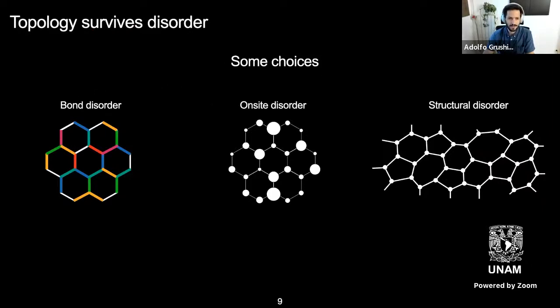But for the moment, let me just highlight some choices you would have to choose a disorder. For example, you have bond disorder, meaning the hopping amplitudes of these electrons hopping in a lattice will be randomly selected from a distribution. Then you have on-site disorder, so the on-site energies are different, maybe there are different potentials at different sites. This is the typical disorder. What's also possible is that not only the hoppings and on-site energies can differ, but the connectivity of the lattice is different. For example, here you see hexagons, but here now you have some pentagon, or some other types of polygons. And it turns out this is quite important, and is actually the central topic of my talk.